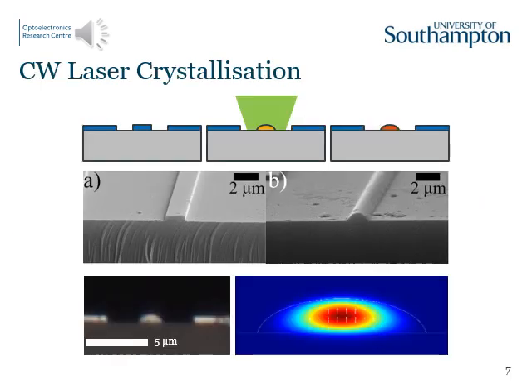This difference in appearance occurs due to the complete melting of the heated volume, one of the advantages offered by the etching of the waveguide structures before crystallization. The thermal confinement that results from this reduces the power requirement, and by ensuring that the waveguide is fully melted, the formation of small crystals, typical to solid-phase crystallization, is avoided. Furthermore, the seeding of crystals from the already crystallized region is encouraged, enhancing the growth of grains along the waveguide length.